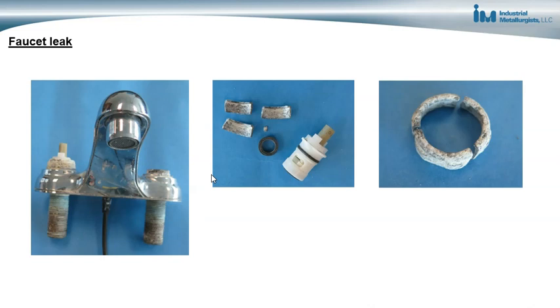There was a small trickle leak past the o-ring that got onto the aluminum nut and onto the brass on the outside. With water in contact with both aluminum and brass, a galvanic cell essentially formed between them. Aluminum becomes the anode in a galvanic cell with brass and will corrode. As the aluminum corroded, corrosion products built up on the inside of the nut, pushing outward, while the aluminum lost material and strength. Eventually the force was large enough to crack the nut; once cracked, it could no longer hold the cartridge, which was then pushed out by water pressure.